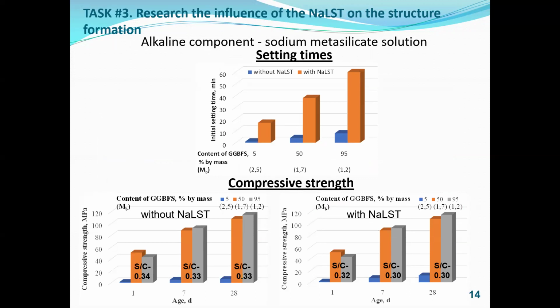With the use of sodium lignosulfonate, the initial setting times of alkali-activated cement systems with modulus basicity 2.5, 1.7, and 1.2 made with sodium metasilicate solution increase from 1 up to 17 minutes, 4 up to 38 minutes, and 8 up to 60 minutes respectively. The initial setting times of the alkali-activated cement systems with modulus basicity 1.2 and 1.7 are rather appropriate. The addition of sodium lignosulfonate to the alkali-activated cement system made with sodium metasilicate solution resulted in some decline of the compressive strength compared to those of the admixture-free cement composition. The strength of the alkali-activated cement system with modulus basicity 2.5 is still low.